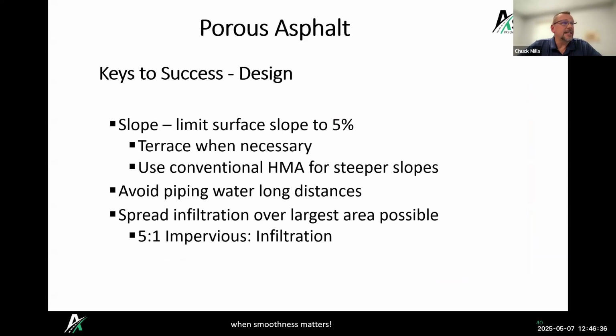Some keys to success for the design. We want to limit our surface slopes to 5%. If the slope where we're putting in a porous asphalt, like a parking lot or whatever, is steeper than that, we want to maybe terrace the parking lot, and then put conventional asphalt in the steeper sections to get between the different layers of parking lots.